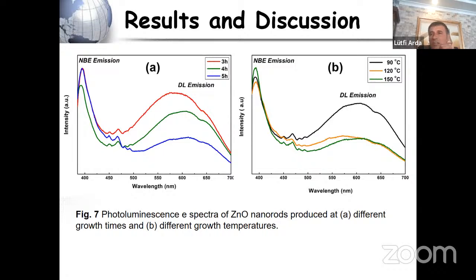Therefore, photoluminescence measurements are performed to analyze the effect of growth time and temperature on the photoluminescence properties of zinc oxide nanorods. A xenon arc lamp is used as the light source, and zinc oxide nanorods are excited at 365 nanometers. Right now in my slide, you can see the photoluminescence spectrum of zinc oxide nanorods produced at different growth times on the left side, and figure B is for different growth temperatures.